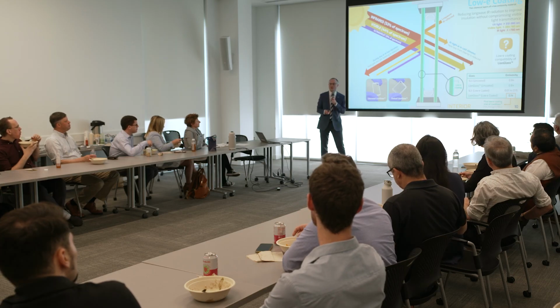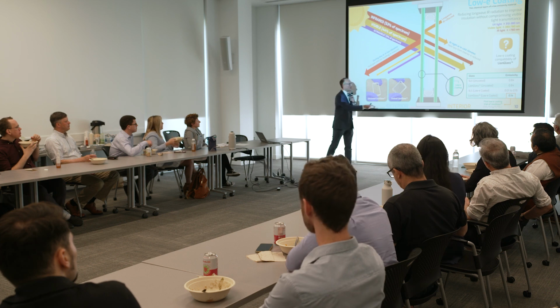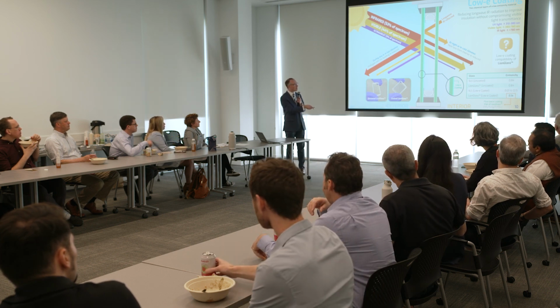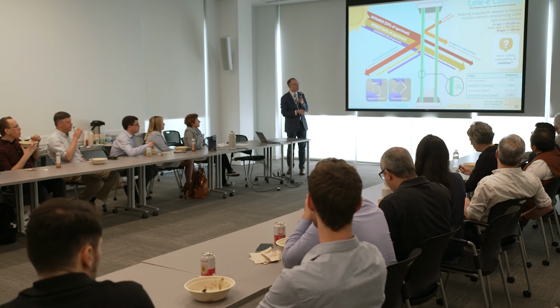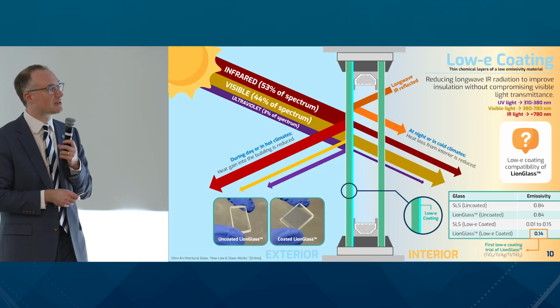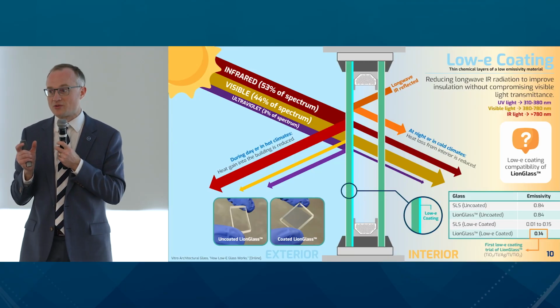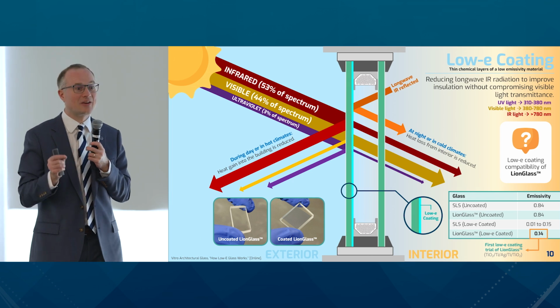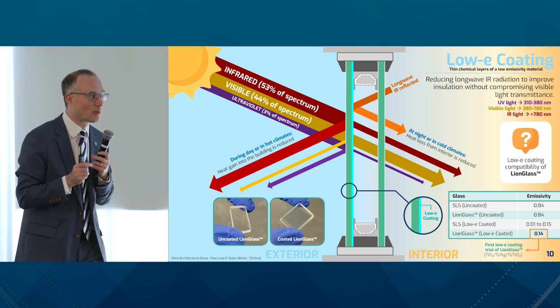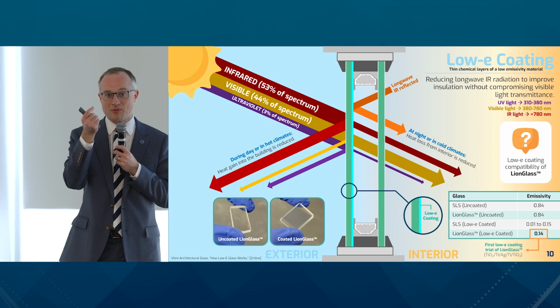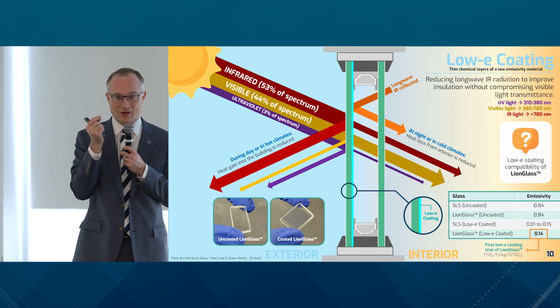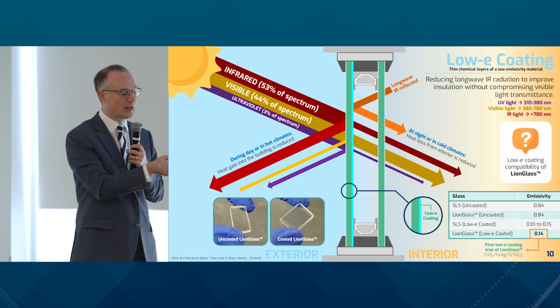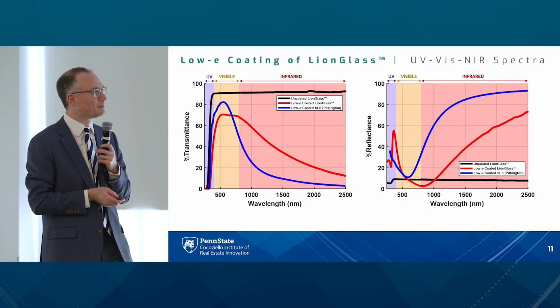And Mehmet was able to show, this is an uncoated Lion Glass here. You can see how beautifully clear it is. And then the coated Lion Glass just to the right of that. And the emissivity values are shown in the table on the lower right. You can see the uncoated soda lime silicate with a higher emissivity, about the same as Lion Glass, and then the coated range right below that. So coated soda lime silicate at an industrial scale goes between 0.01 and 0.15. And already, even with this first lab sample, which is not the quality that one would expect in industry, it's still falling within that range of soda lime.